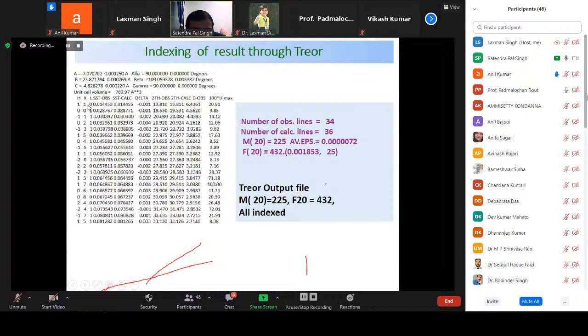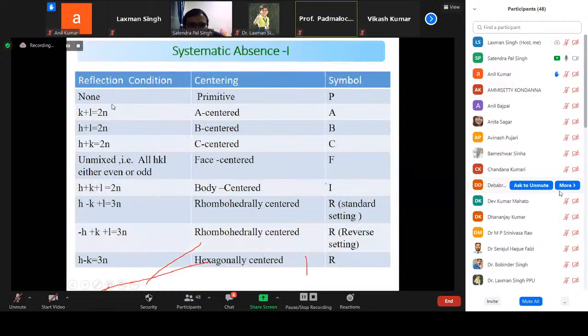So here 110: H is 1, K is 1, L is 0. So this is odd, and 0 is considered even. Here it is all odd, here it is even and odd, so all kinds of even and odd combinations are present here. Now you have to analyze that. If there are no such conditions, then that is called a primitive cell. If there is a condition, for example, K plus L is even in the HKL values, then we say that is A-centered.